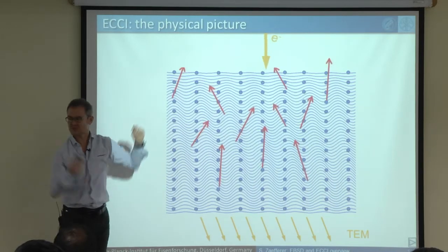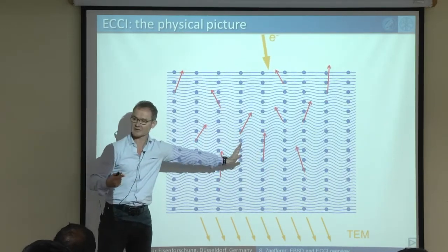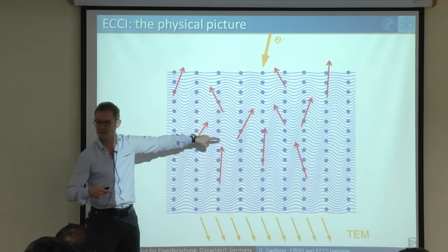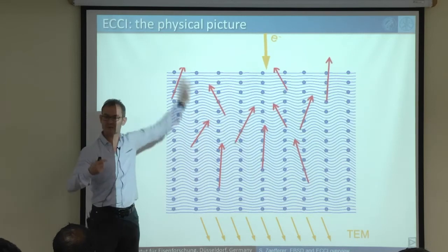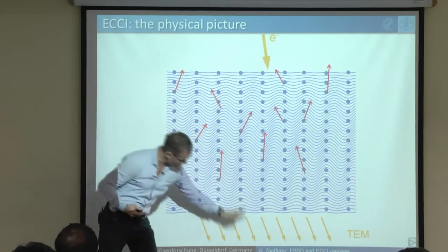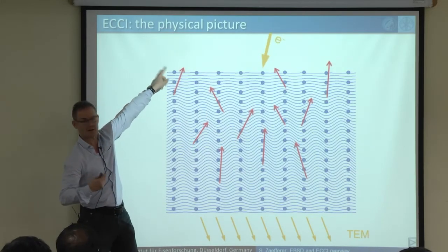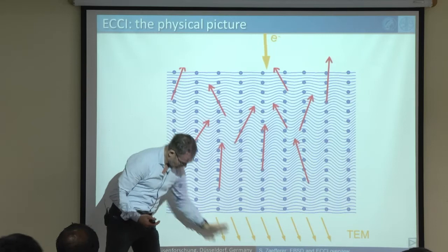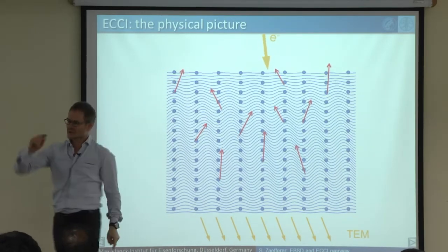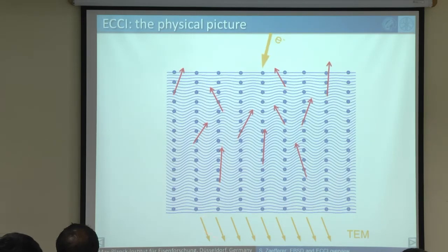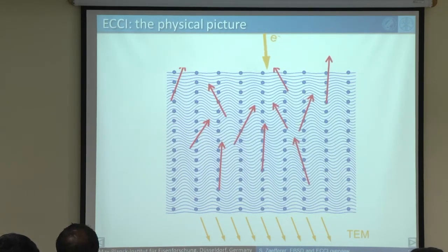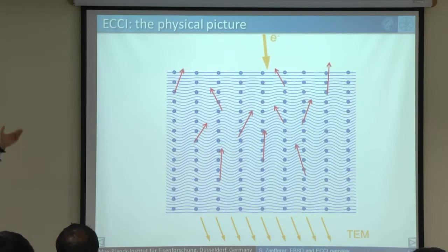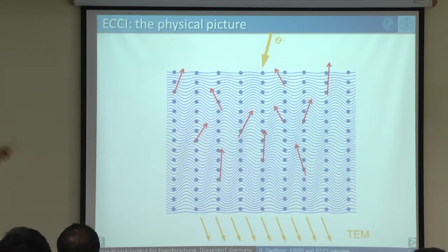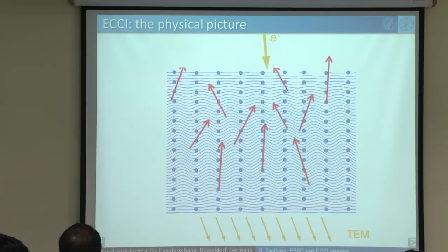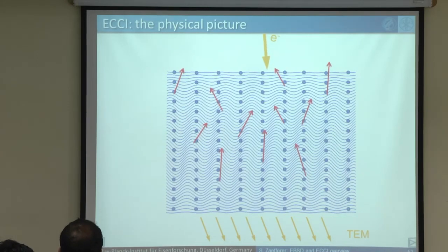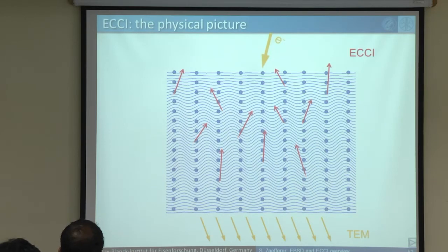And the amount of backscattering depends on how many electrons are at which place. So if there is a maximum of electrons at the nucleus, we will get a lot of backscattering, and if there is a minimum, then we will get no backscattering. And when there is a minimum, we will get strong diffraction and no backscattering here. And if it's inverse, then we'll get no diffraction and strong backscattering there. So we'll actually see here just the inverse of what we see here. It's just the same thing. We're just getting electron diffraction. We are just calling it differently. We call it channeling, but it's in principle the same as TEM, just the contrast is inverted. Something which appears bright here is dark here, and vice versa. So that's in principle the whole story. And there is more to know, but not for today.